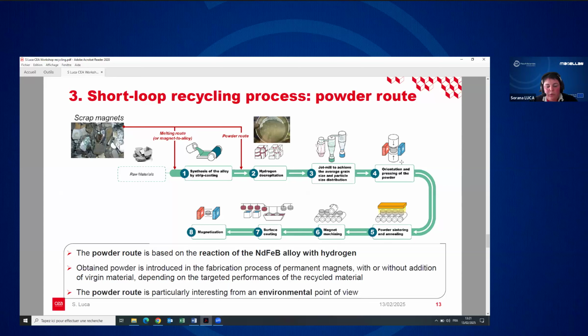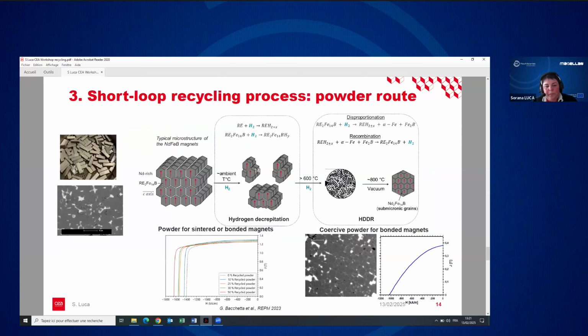If we talk now about the powder route, the scrap magnets will enter the step of pulverization during the conventional process to fabricate new magnets. The powder route is based on the reaction of neodymium iron boron alloy with hydrogen, and it is particularly interesting from an environmental point of view. The reaction can be described here. Here we have some scrap magnets with the microstructure of the magnet, with magnetic grains surrounded by non-magnetic rare earth rich phase. These magnets will react with hydrogen at ambient temperature. The reaction will pulverize the material, and this reaction is called hydrogen decrepitation.